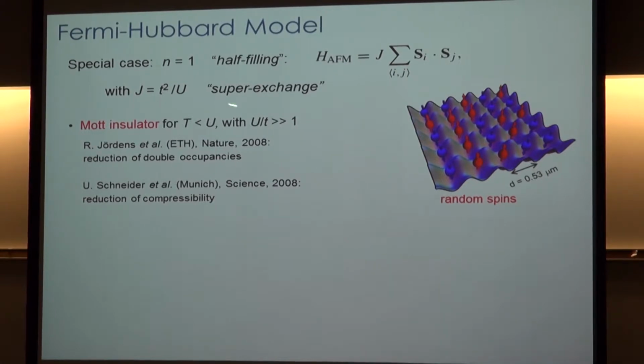For temperatures that are much higher than this superexchange energy, but less than U, the interaction energy, it is known that this Hamiltonian will produce what's called a Mott insulator. A Mott insulator is different than a standard band insulator, which we have in most materials, in that it's interaction driven. So it's an example of a strongly correlated phase. It occurs when the temperature is less than U, the interaction strength, and with U over t much bigger than 1. So it's strongly interacting and the hopping is not that big.